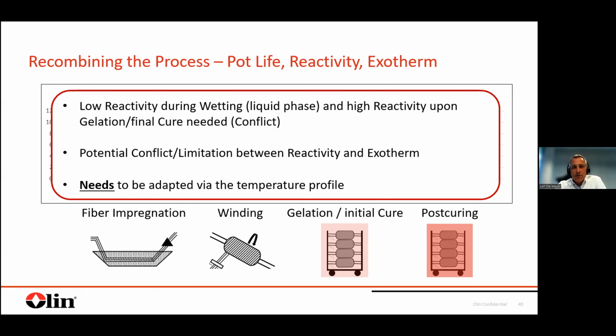But this again needs to be balanced with the other parameters. And this is a little bit key of my statement here. There are always potential conflicts and limitations between reactivity, viscosity, and exotherm. And in the end, this needs to be adapted via the temperature profile. At the same point of time, seeing this conflicting and complex profile of requirements, we can already assume at this point of time that there may not be the one-fits-all solution for a good epoxy filament winding system, and that depending on the process and different other parameters, a certain portfolio and adjustment is needed.